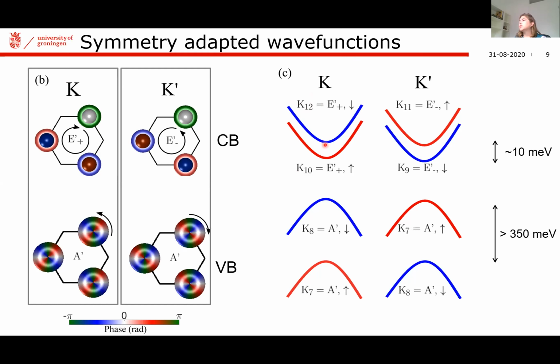Now, what you can notice also is that there is a splitting between the two spin subbands, both in the conduction band and in the valence band. And this splitting is much larger in the valence band than it is in the conduction band. And that you can understand again from this representation of the Bloch wave functions. Right? So like I told you, in the valence band, there's an orbital angular momentum around each atom coming from the atomic wave functions. And this large orbital angular momentum actually gives rise to this large spin-orbit coupling.